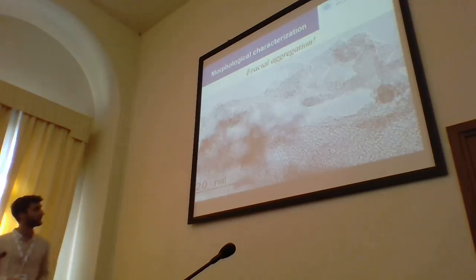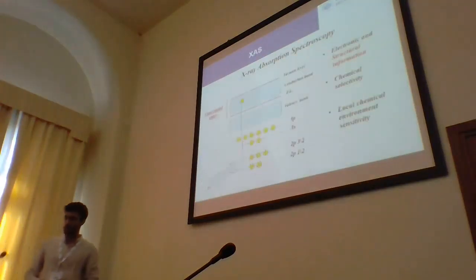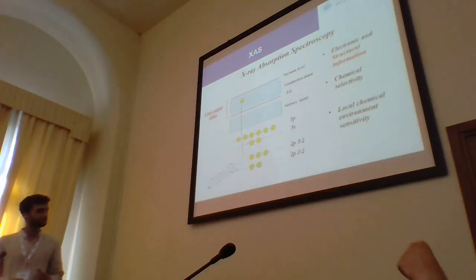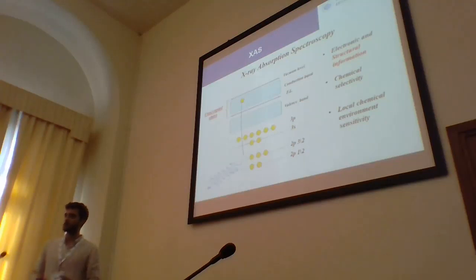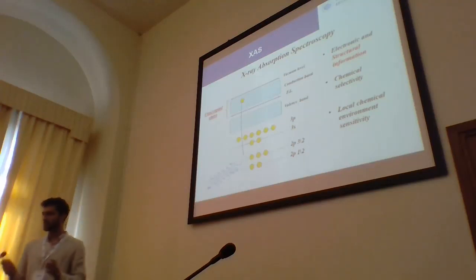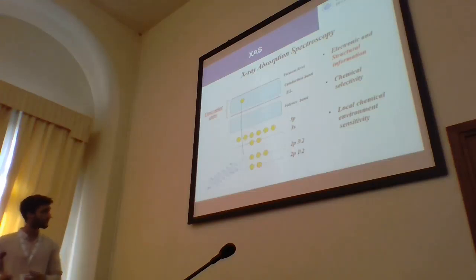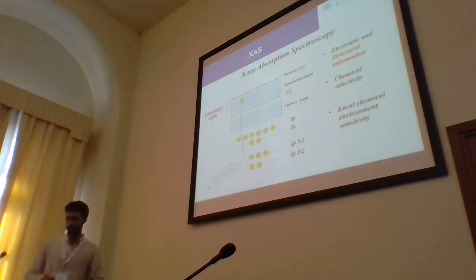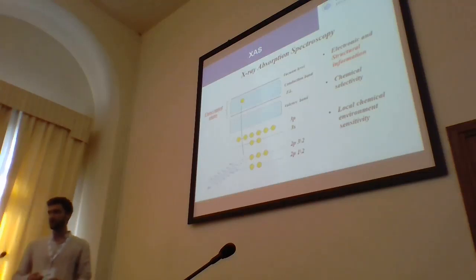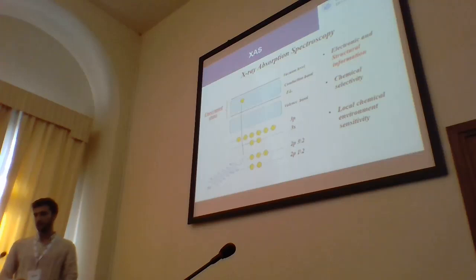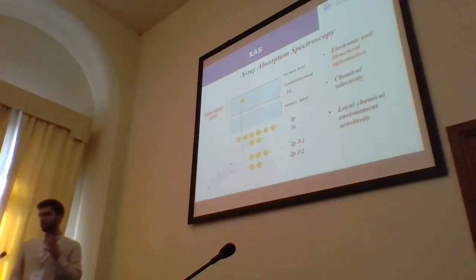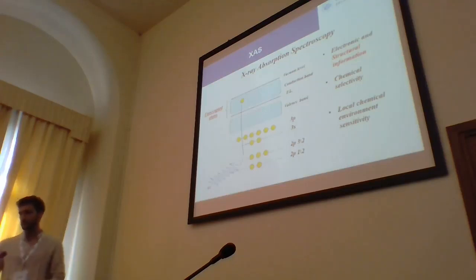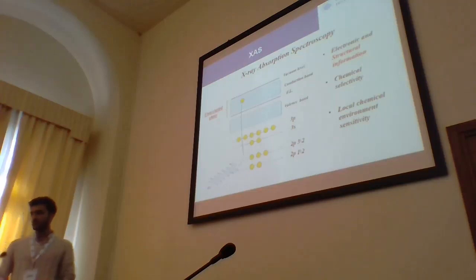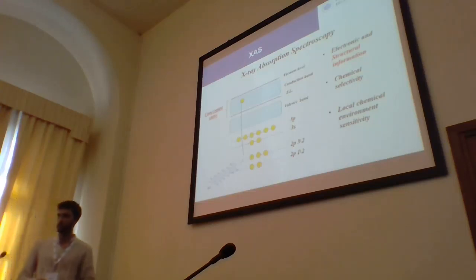For example, performing absorption spectroscopy on our sample, we see that actually our samples are not crystalline. If any one of you is not acquainted with absorption spectroscopy, it works in the following way. You illuminate your sample with a photon beam, and you pass across the resonance of your sample, and in this way an electron is removed from a core level and is placed in between the Fermi level and the vacuum level. It means it's put inside an unoccupied level. So this technique is chemically selective, and it gives us information about the electronic structure and the crystallinity of our sample.